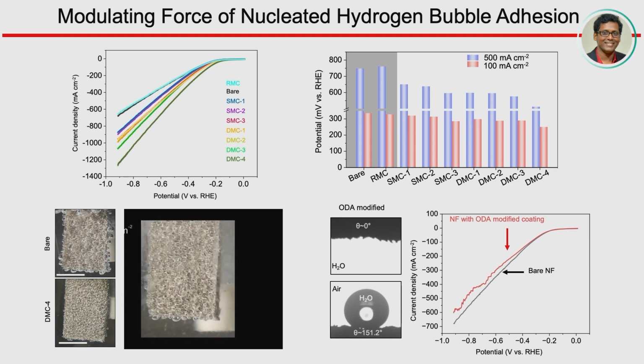When you go for the ODA modification, the interface suddenly becomes bubble-philic, the affinity for the bubble will be much higher, right? The contact angle of the bubble will be much lower, right? In that case, you see the performance is even poorer than the bare. So with the same coating, it's just the modifier you change, you play with the bubble repellency or bubble affinity. Depending on that, you see the improved performance or the poor performance, right?